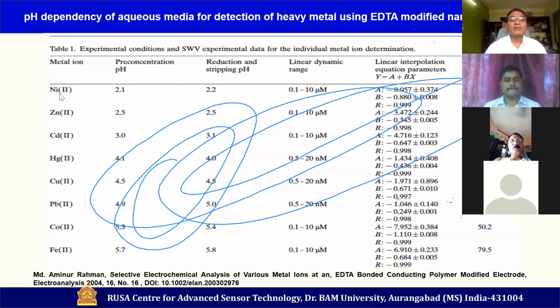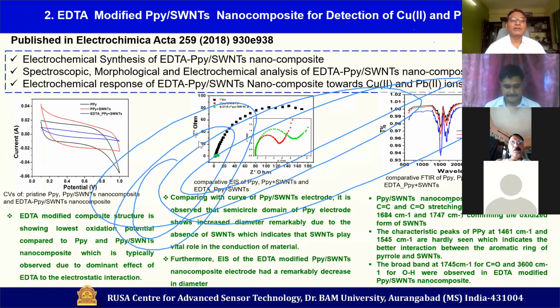pre-concentration as well as reduction, then your device can be very selective to different ions. Let us say Ni. For Ni, if you could manage pH 2.1 for pre-concentration and 2.2 for reduction, obviously you will be able to fine tune your device to Ni. It will be highly selective. So this is some of the data which we have already explored while doing experiments. And this is another work which we have already published in 2018 in Electrochimica Acta.